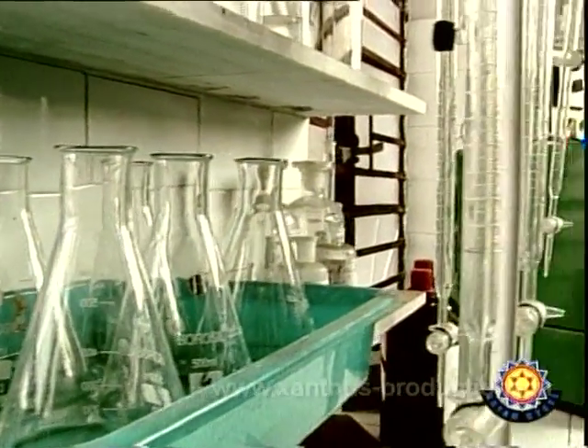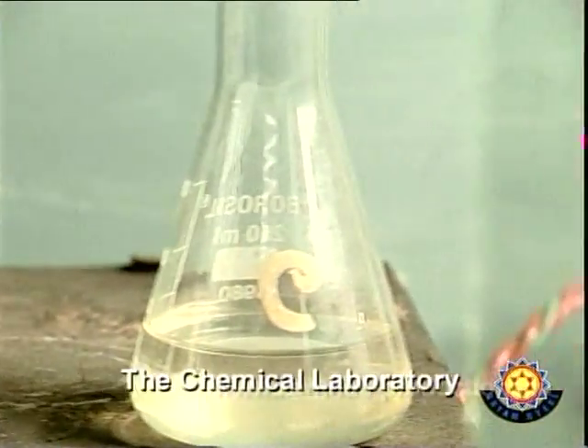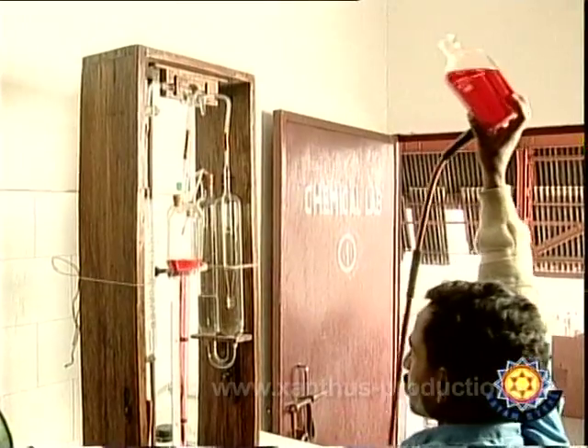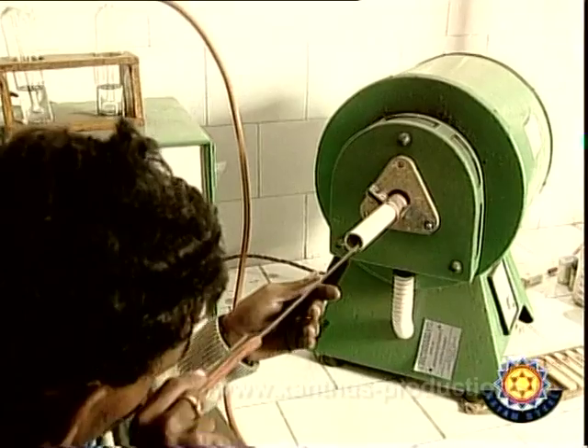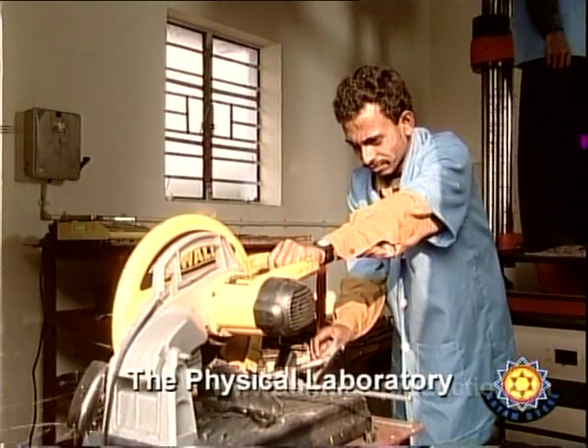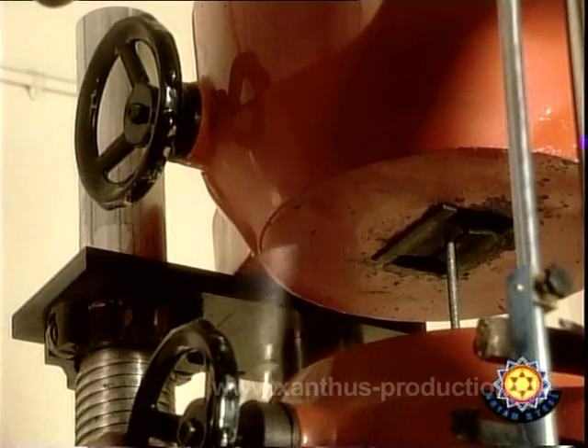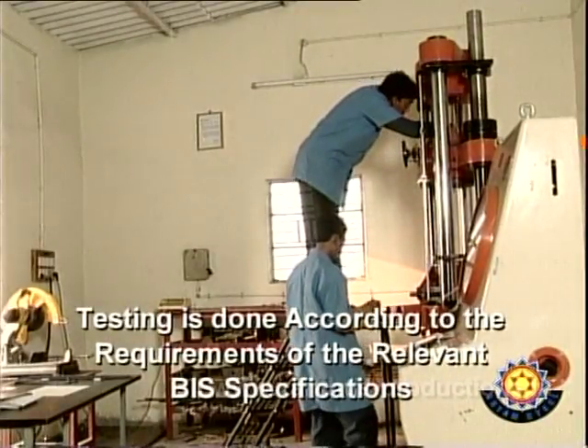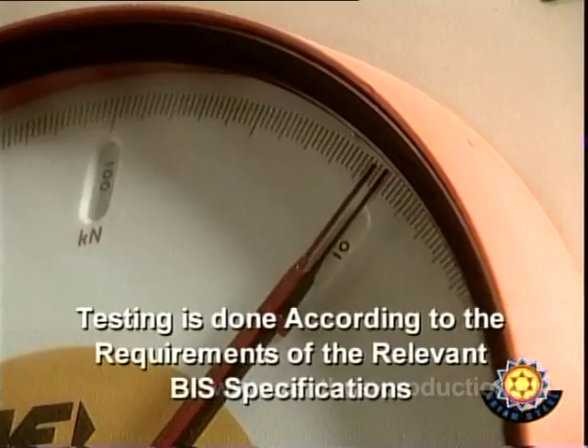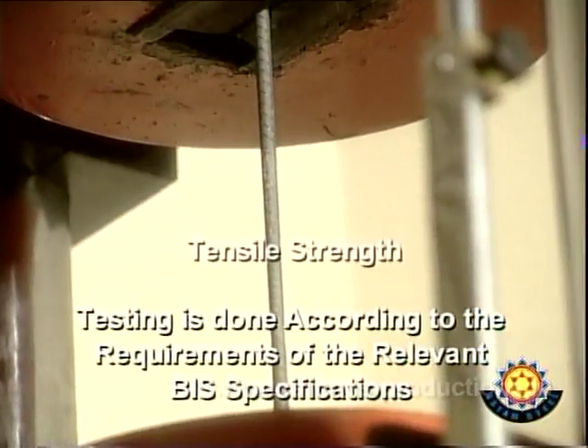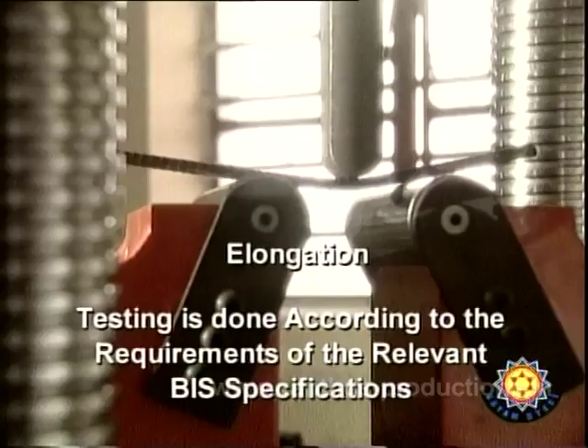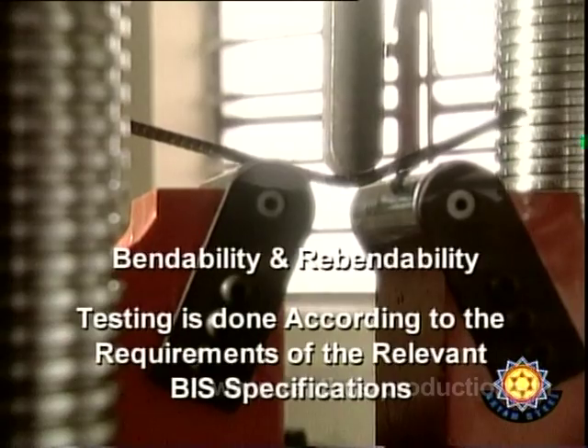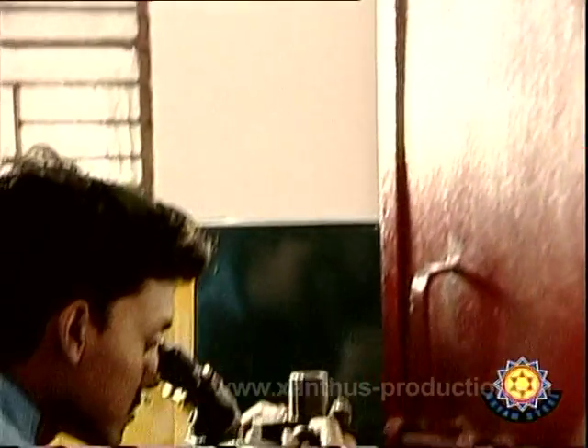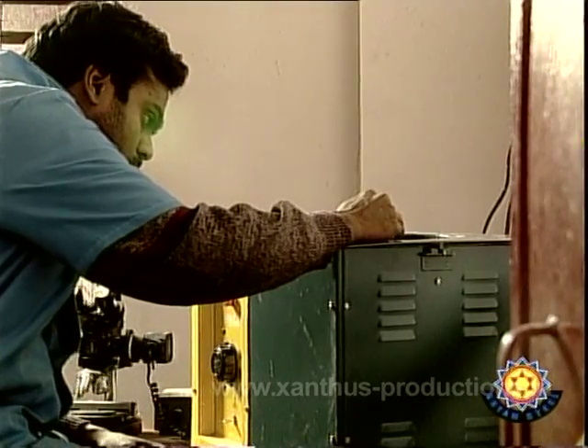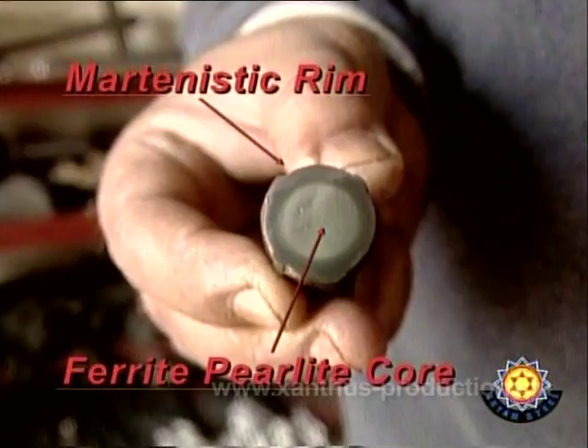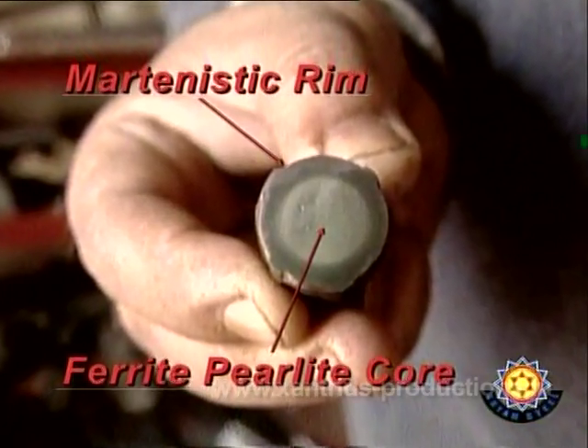In the chemical laboratory, the samples are analyzed to detect the content of sulfur, manganese, carbon, phosphorus, and silicon. In the physical laboratory, the bars are tested according to the requirement of the relevant BIS specifications, like proof stress, tensile strength, elongation, and bendability. The metallurgical tests performed on the samples detect the formation of the outer martensitic rim and the inner ferrite pearlite core properly.